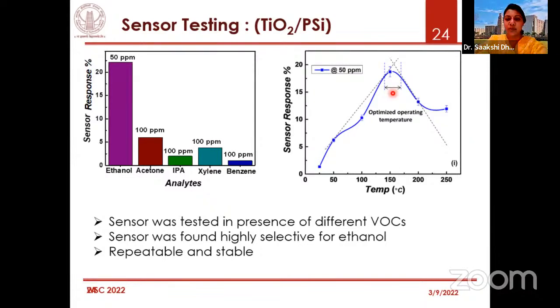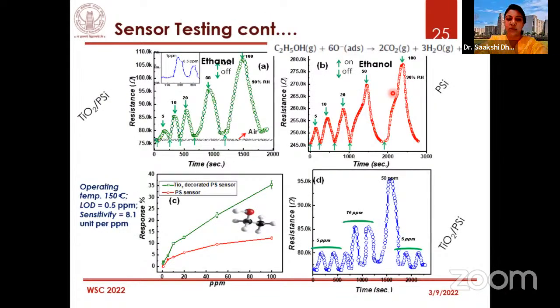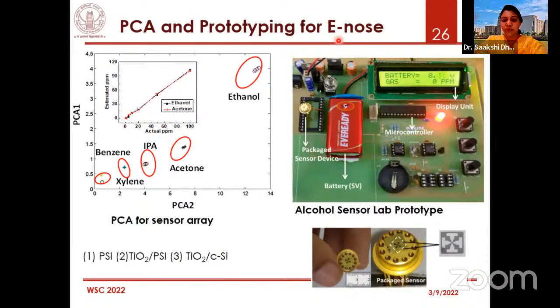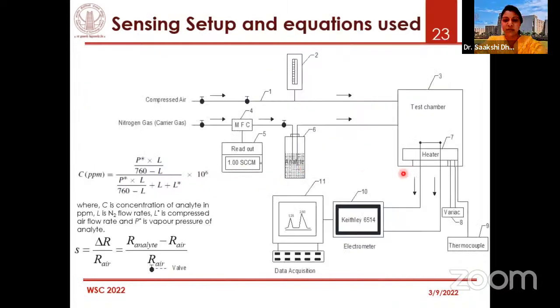So that's how we started to work on something called an electronic nose, right? So I'll come to that slide. I would like to show the sensing setup that we used. To make sure that we are simulating the human breath, we used compressed air, which could give us almost 95 to 98% humidity inside the chamber. And nitrogen gas was used as the carrier gas, which would bring the vapors inside, right? And by controlling the compressed air flow rates and the temperature of the analyte, so that we could control the vapor pressure, which in turn helped us control the concentration, we could see that we are able to achieve ppm to sub-ppm level.